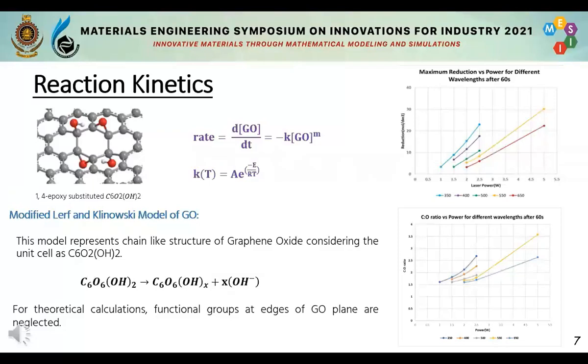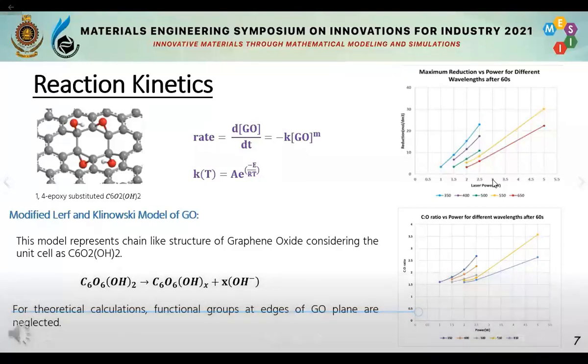As the next step of our project, we modeled reaction kinetics using the results of the temperature distribution modeling. Here we used the rate equation and Arrhenius equation for calculations. We considered the modified Lerf and Klinowski model of graphene oxide for our purpose. This model represents the chain-like structure of graphene oxide, considering the unit cell as C6O2OH twice. For theoretical calculations, functional groups at the edges of the graphene oxide plane such as carboxyls and carbonyls are neglected. We separately calculated reaction kinetics for selected wavelengths and powers. Then we plotted graphs in order to find maximum reduction for different parameters and carbon to oxygen ratio for different lasers.